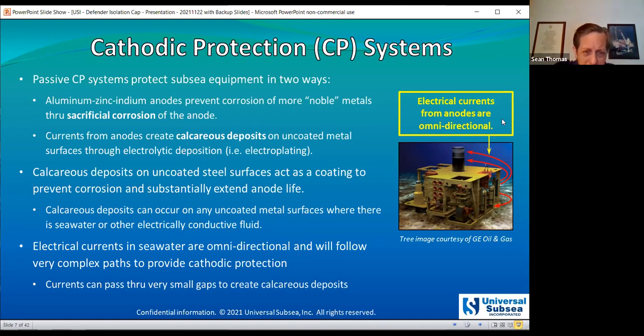These calcareous deposits that occur on uncoated steel surfaces act as a coating to prevent corrosion of the steel, and they will actually substantially extend the anode life. So this calcareous deposit phenomenon is a necessary phenomenon. It's beneficial on things like pipelines where coating has been removed, but on any tightly toleranced interfaces and any seal surfaces, calcareous deposits are highly undesirable, as we'll look at.